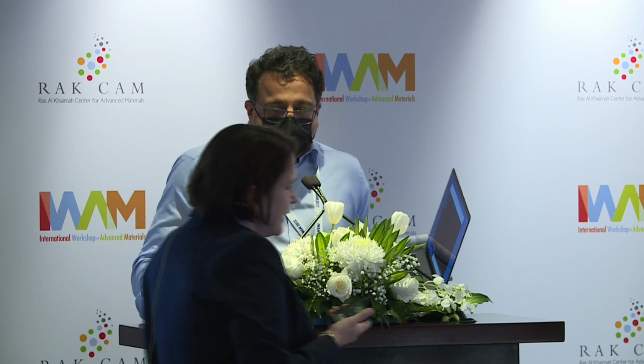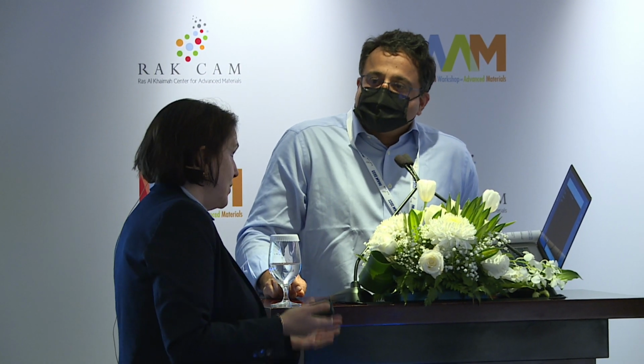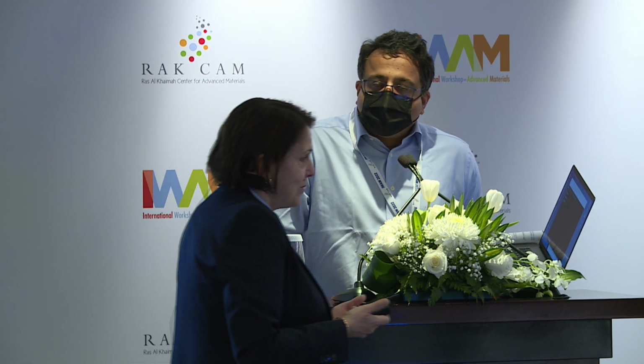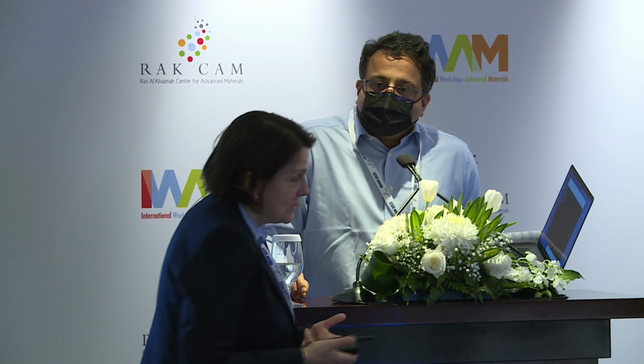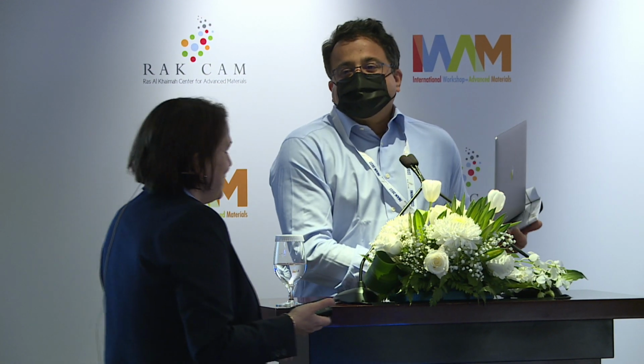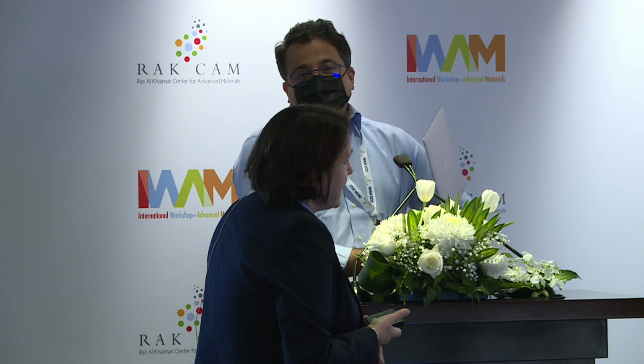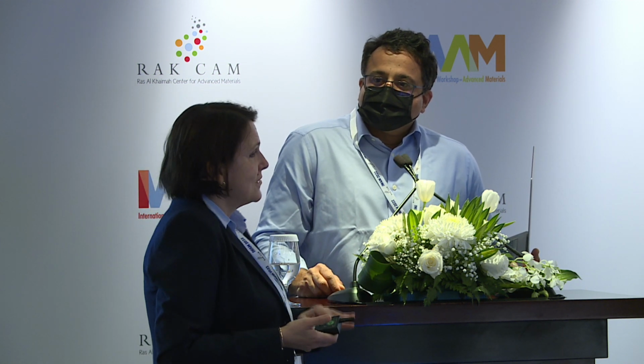Yeah, here it's really like we have the palladium and the platinum, you are right. So we really have to investigate more what is the origin, also for the chiral adsorption, the preferred one, whether it's the surface state. I went over my last slide maybe too fast. So we want to see, is this a surface state, is this the orbital angular momentum which plays a role, or is it simply chiral structure? But in white semimetals, we don't have a chiral structure. So we could then finally go on, but I want to go step by step because we really want to understand. But you're right, we are now looking for other systems, and therefore I also went very fast over the twisted graphene. But you know, if you take twisted graphene, it's chiral.